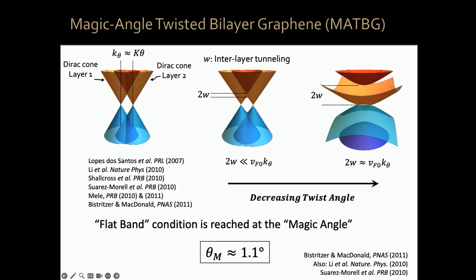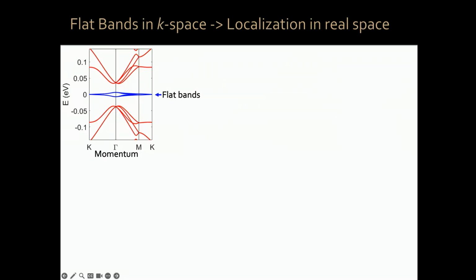This is energy versus momentum, projected in one dimension. And you can see that these are flat bands. This is no longer these steep Dirac cones. It's something very flat. It's not completely flat, but it's much flatter by orders of magnitude with respect to the original graphene dispersion. So the electrons in this magic angle graphene have very little kinetic energy compared to the original one.